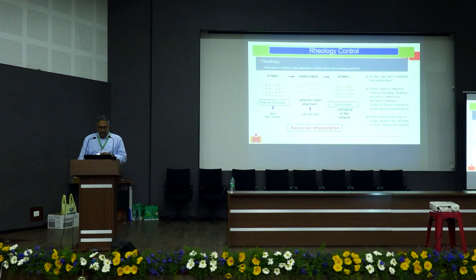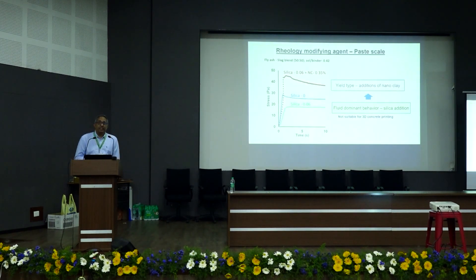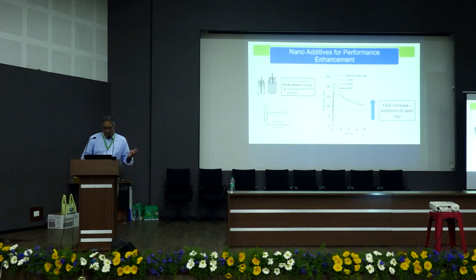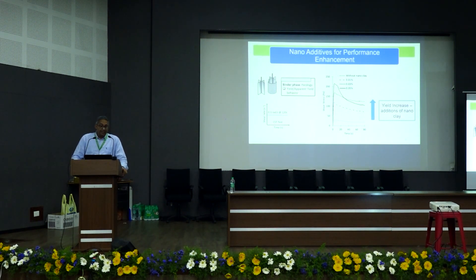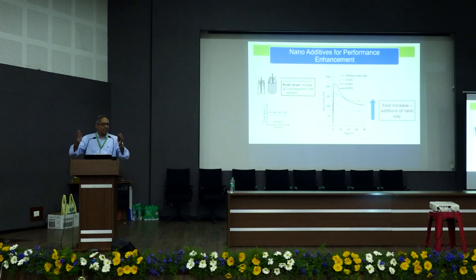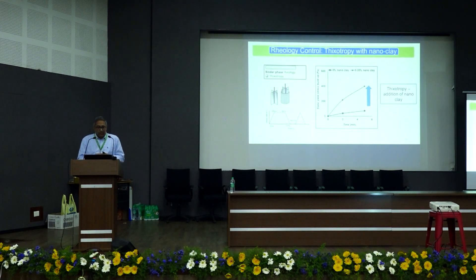Going further, I can improve the yield stress by adding more nanoclay. You can see the stress versus time response with different quantities of nanoclay. If I just add about 0.05% nanoclay, I start getting a very serious amount of yield stress — about 200 to 220 pascals, which is considered excellent for shape retention. A material with this yield stress, if extruded from a nozzle, will beautifully keep whatever shape I give it.